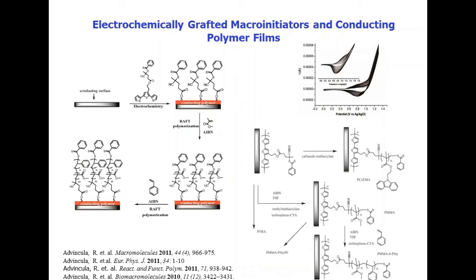All right, so from here, we actually reported the use of electropolymerizable macroinitiators. What these are is monomers that can be electropolymerized, in this case, thiophene into polythiophene, which contains a RAFT chain transfer agent. This RAFT initiator can be used to polymerize polymethyl methacrylate, as shown here. And then we can make a block with polystyrene on a grafted brush, as shown here. So we have polymethyl methacrylate, polystyrene grafted on the surface. Or in this case, we can combine a carbazole and a styrene. And so these are what we call electropolymerizable macroinitiator polymer brush synthesis.